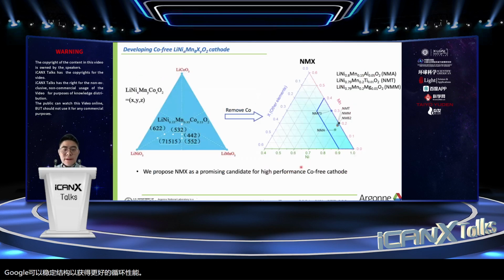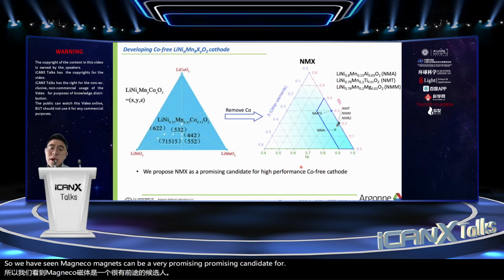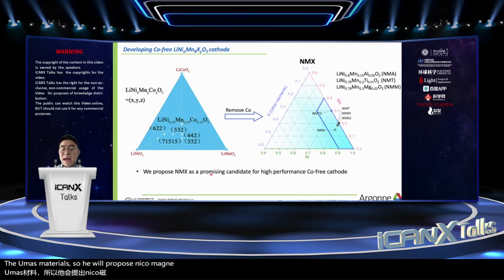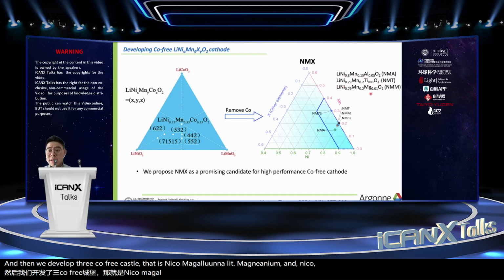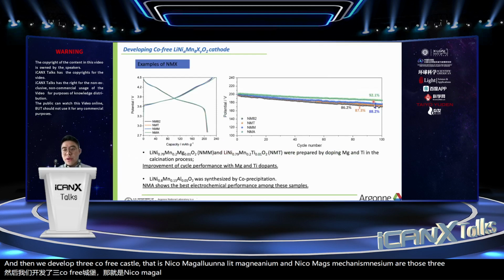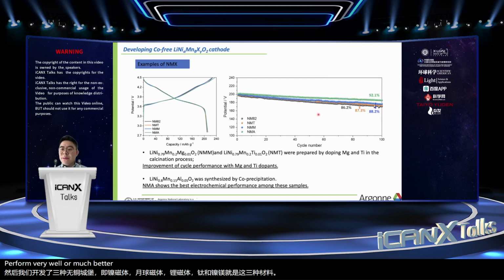So we say nickel manganese can be a very promising candidate for the cathode materials. Here we propose nickel manganese acts as a next generation cobalt-free cathode, because when we remove cobalt, we can have much lower cost for the current batteries. And then we developed three cobalt-free cathodes: nickel manganese aluminum, nickel manganese titanium, and nickel manganese magnesium. Those three materials perform very well, much better than the nickel manganese and also nickel cobalt.